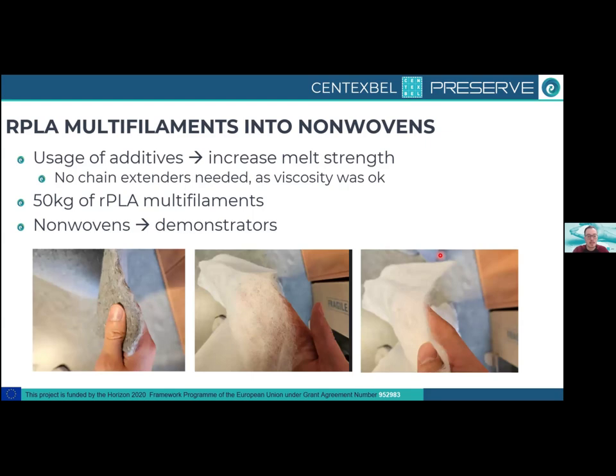Now, using these additives, we will increase the melt strength. These additives are not chain extenders because the viscosity of just the RPLA itself was good. But these are additives specifically tailored to increase the melt strength of this PLA, because going from a film grade PLA to a multi-filament grade PLA where you really stretch the PLA a lot, this is the main problem. But we have succeeded in the project to make 50 kilograms of the RPLA multifilaments, which we then made